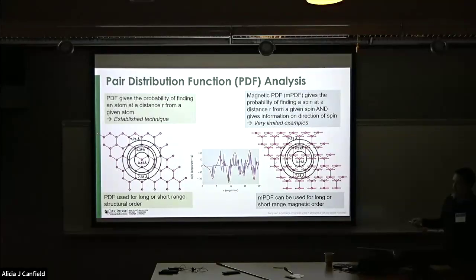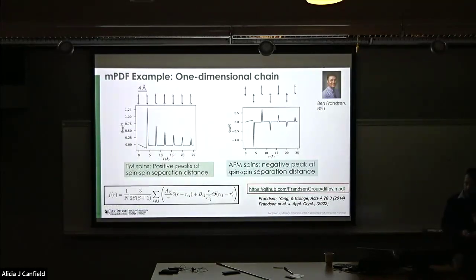These two differences, the red and the blue, is how you normalize your data. So the blue is what you really want. This is if you can isolate the magnetic scattering and account for the form factor and correct everything properly, you get improved resolution. If you don't do that, you get the red, you get worse resolution. So Ben Frandsen, he was working with Simon Billinge for his PhD, and he developed this technique. And we're using his software down here, so I want to acknowledge a lot of the work that he's been doing.